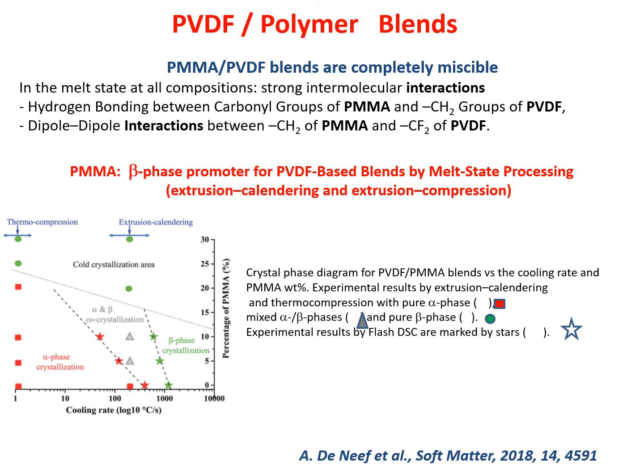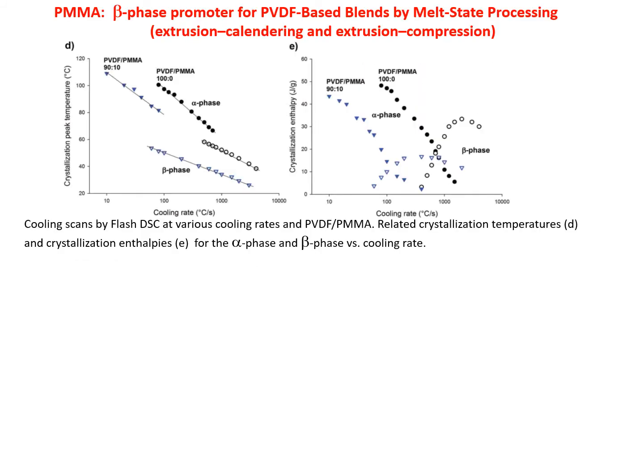So you have to cool at very high temperature speed, and you can also have cold crystallization here. In addition, Jean-Marie's group also investigated the cooling, the crystallization peaks, and also the crystallization enthalpy versus the cooling rate, and could see that in different PVDF-PMMA content, you had some beta phase, even at 5% of PMMA, which was very interesting as a result.